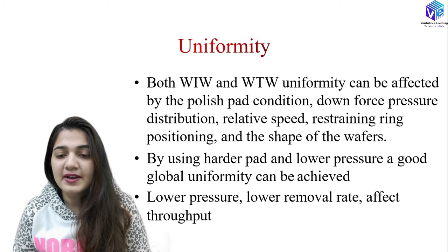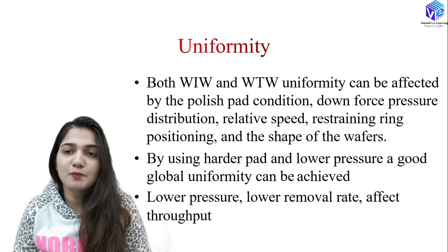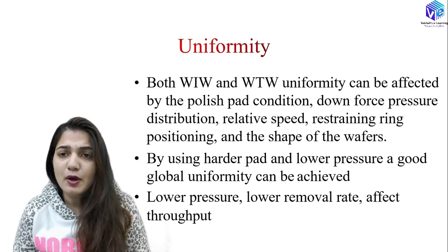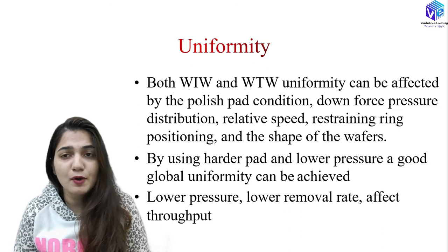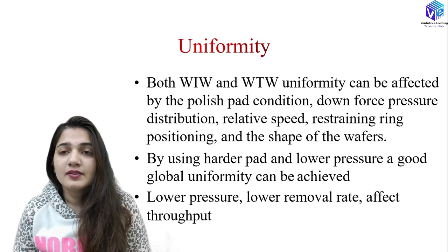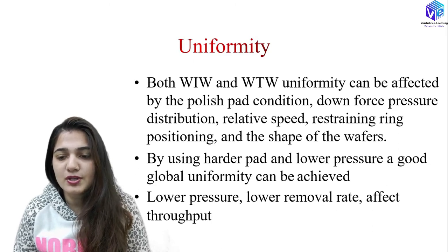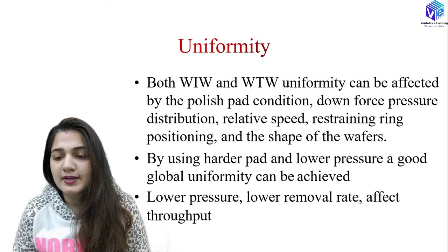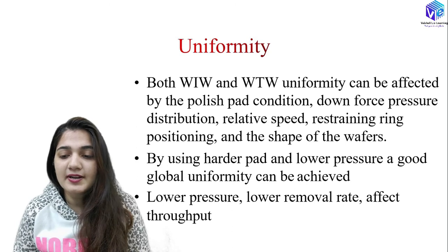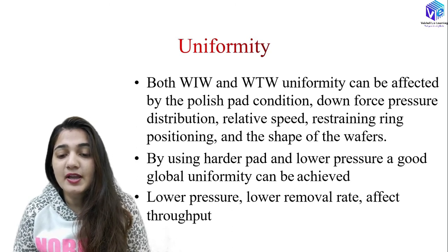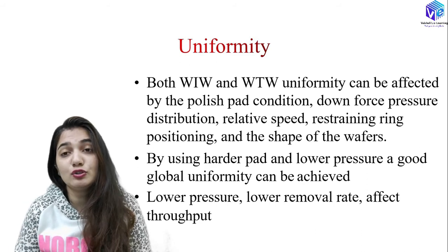Both within-wafer and wafer-to-wafer uniformity can be affected by the polishing pad condition. A harder polishing pad gives faster removal rate and a more planar structure. Uniformity is also affected by down-force pressure distribution, relative speed between pad and wafer, restraining ring positioning, and wafer shape. Using a harder pad with lower pressure gives good global uniformity, though lower pressure and lower removal rate affect throughput.